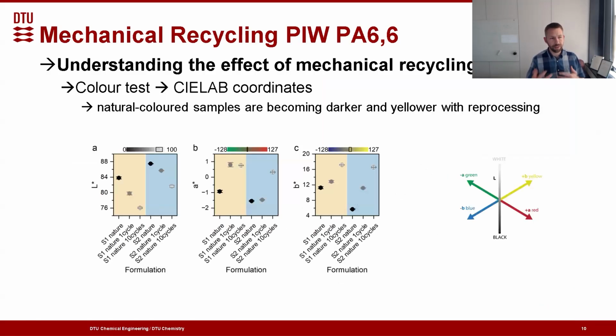If we go at this in a little bit more academic fashion, we can actually measure through color tests the impacts on lightness, on green and red color, blue and yellow color, where we can clearly see that between these different cycles, we do have a significant change in all the compounds. But what is maybe interesting here is also to notice that the suppliers don't change the same. So already from the supplier side, there is an effect on the different coloration, and we can see that this is not at all the same.